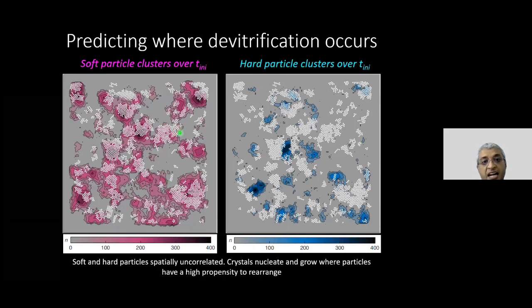And you will see that crystals essentially grew in a region which I could already classify even before the crystal grew as being soft. All right. So where crystals grow in a glass has a very strong correlation with the underlying structure of the glass, and that's what these images are trying to show.